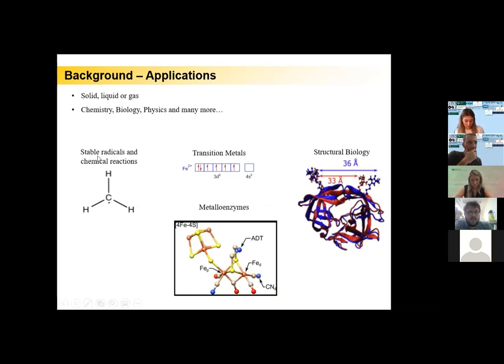I'll give you some examples. We can study stable radicals and radicals that are formed during chemical reactions. We can study transition metals such as iron 2+, and also these metals when they are inside complexes, such as metalloenzymes. Most of my work was done towards structural biology applications. Usually biological molecules are diamagnetic, so we have to tag them with some kind of radicals to see them in EPR. We can tag them with one radical and study it, or if we tag it with two radicals, we can measure the distance between the radicals. With the current method, we can measure up to 70 nanometers between them, and then we get some kind of distance distribution, and it helps us solve the structures of the molecules.